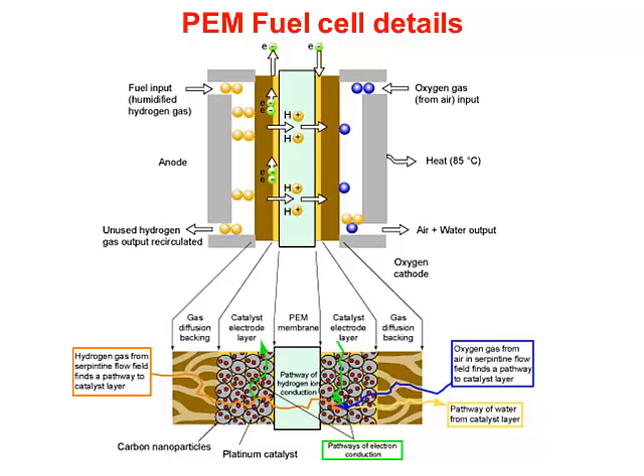The challenging part is this section here. To minimise the use of platinum, which is obviously an expensive material, we've got platinum catalyst particles, typically 2 to 3 nanometres mounted on 30 nanometre carbon particles. These have to provide electrical continuity, and at the same time you have to have ionic continuity to transfer hydrogen ions through the system. Interspersed with these particles is the ionomer, or conducting polymer. So you can see the challenge: you've got to get interspersion of the polymer, simultaneous electrical conductivity and ionic conductivity, and you've got to get the gases in and the water out. Johnson Matthey are probably the world leaders to some extent in developing these with high efficiency.